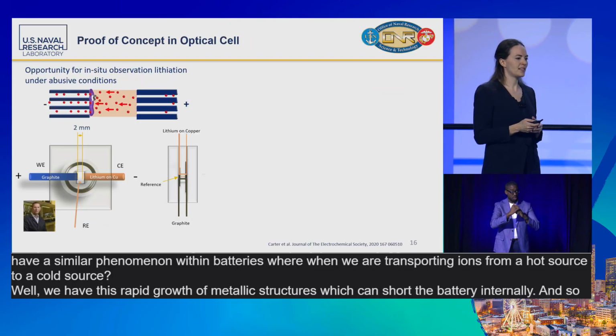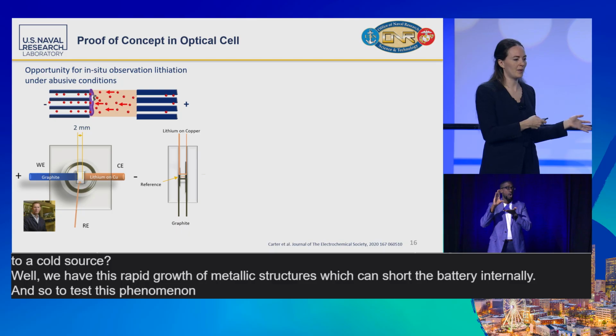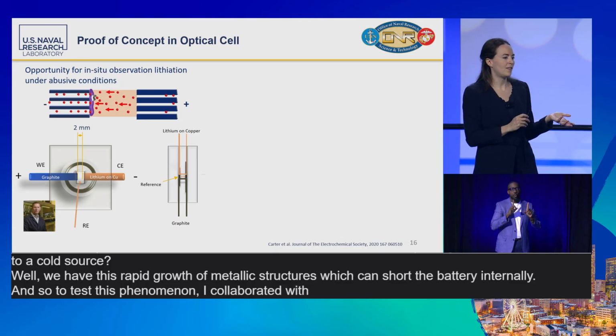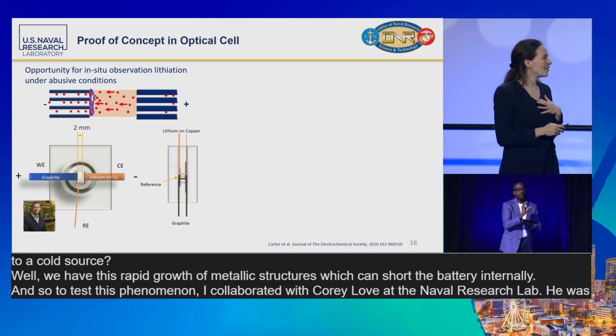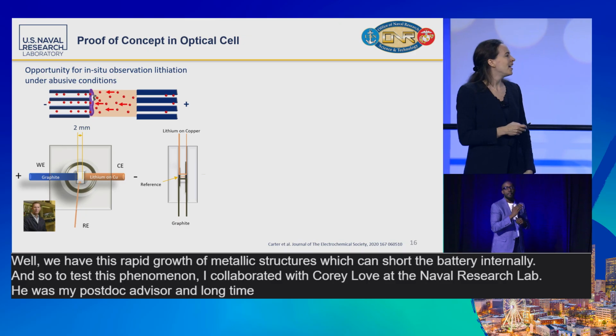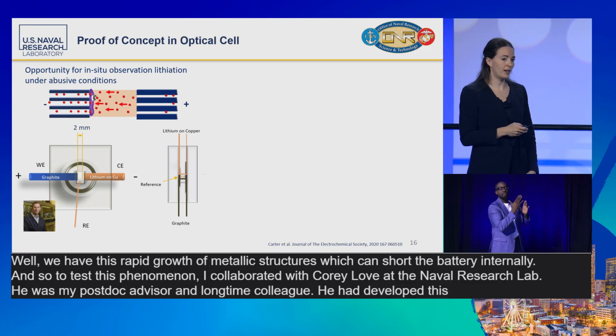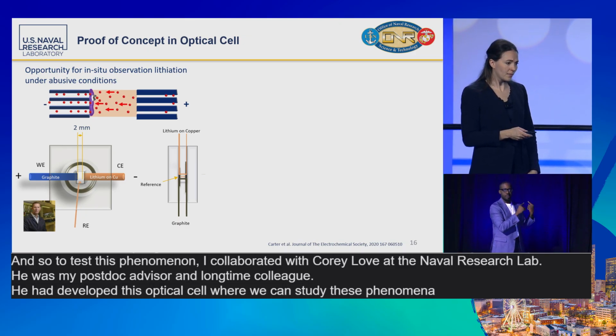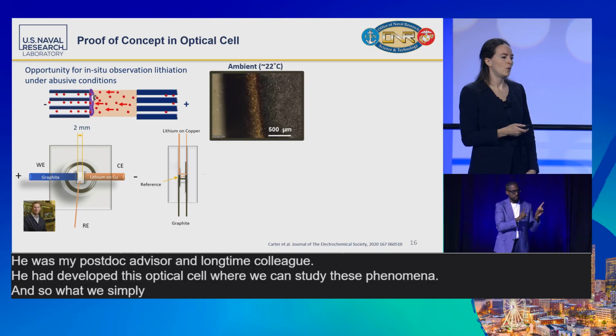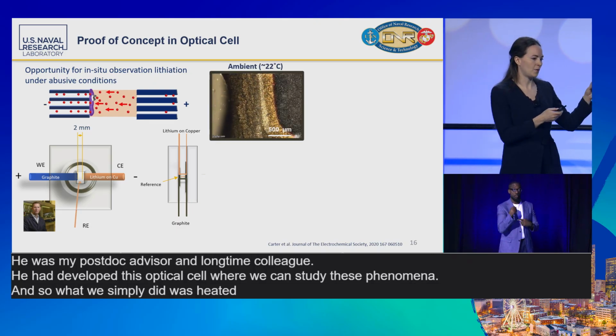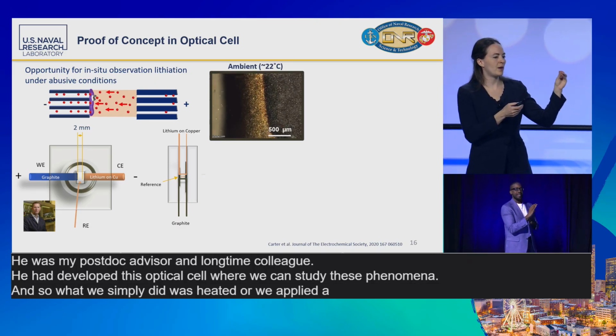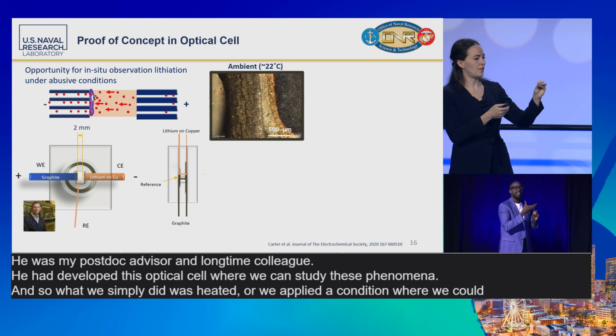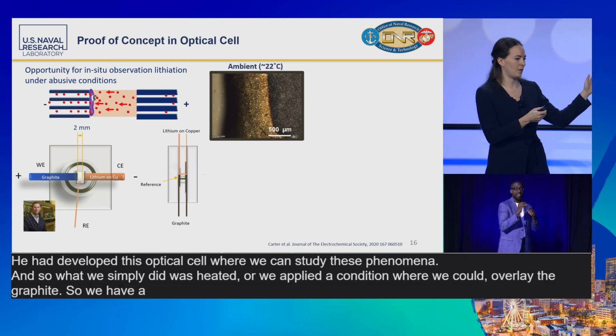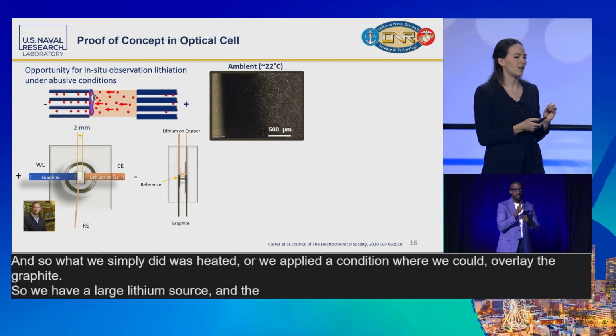And so to test this phenomenon, I collaborated with Corey Love at the Naval Research Lab. He was my postdoc advisor and longtime colleague. He had developed this optical cell where we can study these phenomena. And so what we simply did was we applied a condition where we could over-lithiate the graphite. So we have a large lithium source and the graphite target.